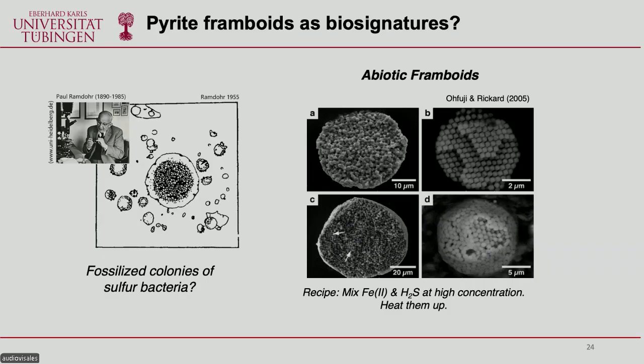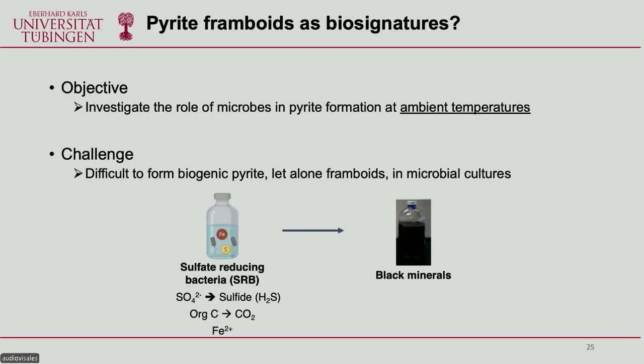know the recipe. And the recipe is just that you mix iron, you mix sulfur at high concentration, and then you heat them up. Typically, you require temperatures over 80 degrees Celsius, which means that this may not be fossilized colonies of sulfur bacteria. But that doesn't mean that microbes are not involved in their formation at all. What we want to know is, can microbes really form pyrite framboids or not, especially at ambient temperatures, because this has not been shown experimentally.